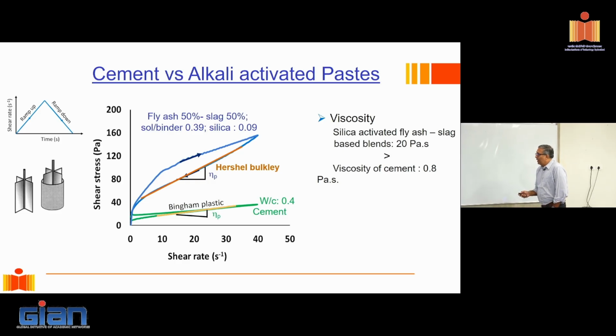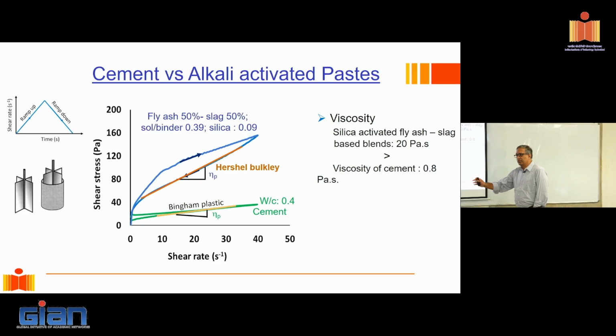But if I take one of these alkali activated materials where I have 50% fly ash and 50% slag, and I'm taking a solution to binder ratio of 0.39. That is, 61% of this paste is solids, which is fly ash and slag, taken in a proportion of 50-50, and 39% of the paste is activating solution. What is the activating solution made up of? Well, it is a combination of sodium hydroxide and sodium silicate, such that I get a silica content of about 0.09. That means 9% of the solution is dissolved silica.